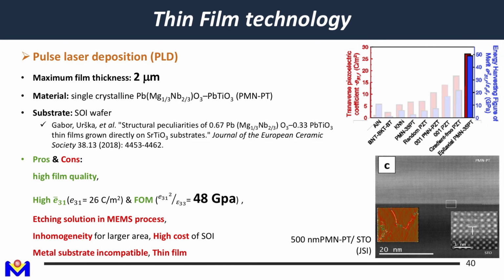And then thin film technology. This is the PLD, pulsed laser deposition, application method I just mentioned from the European Piezoelectric MEMS program. You can see here it can reach a very high figure of merit, and it is so far, as far as I know, the best single crystal thin film piezoelectric material with the best piezoelectric performance. But the disadvantage is the following process is very difficult because you are facing a lot of very hard material to etch. So I got a partner in Norway, SINTEF Research Institute, and we actually had a project working together. But in the end, they actually failed to do the following fabrication as energy harvester.